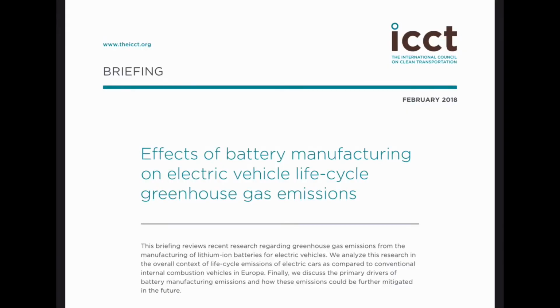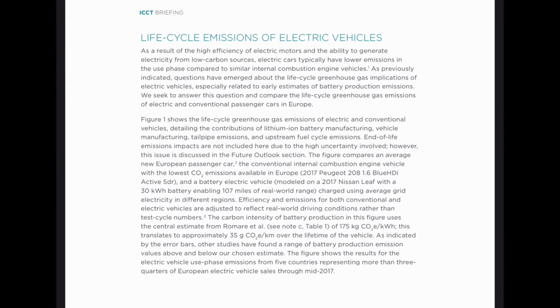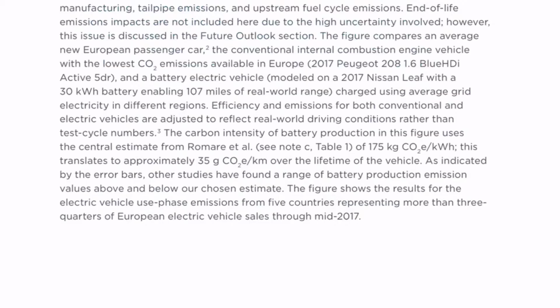Now, one other important study with regards to the manufacturing of lithium-ion batteries comes from the ICCT, which is the International Council on Clean Transportation. Now, this study is a little bit more current, from February of 2018, and here they look at a range of different studies and come up with an average of 175 kilogram equivalent CO2 per kilowatt hour, which is right in line with the IVL estimates of 150 to 200.